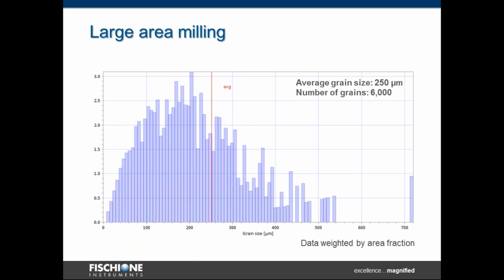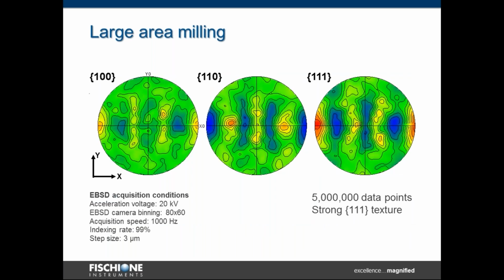So you can imagine how good the statistics you will get being able to mill such a big sample, 50 millimeters in diameter. Another slide shows a set of pole figures plotted from 5 million data points, showing a very strong texture along the 111 direction for our copper bar. With that conclusion, I will turn over to Paul.